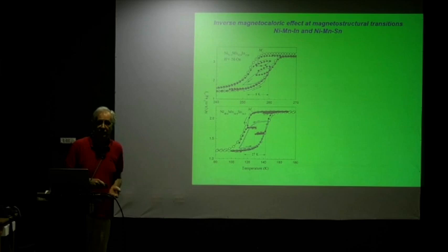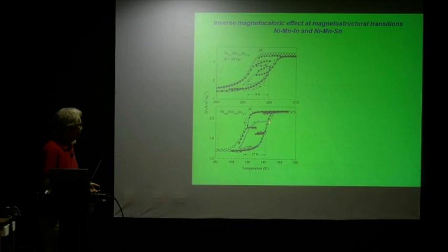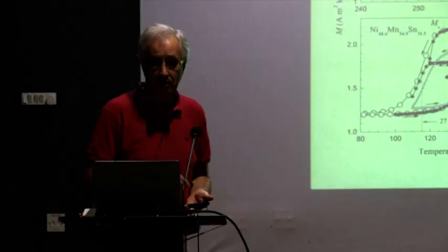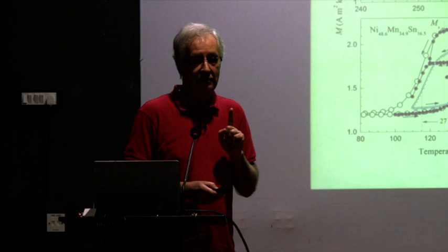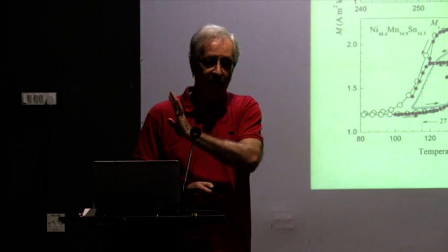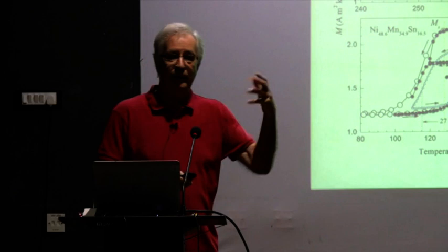So you do this. If you go to some temperature around here, like this blue one, and then go all the way back down again, you have to reduce the field very much in order to be able to see anything. But in very many cases, what you do is you get stuck in the hysteresis. So when you measure, we're not just measuring up and down, but we're measuring up and down, up and down, up and down. We're cycling the thing. Because a refrigerator cycles, and we have to know what the magnetocaloric material is doing when we are cycling these things. Is it operating properly?